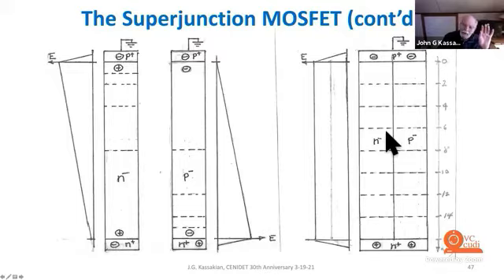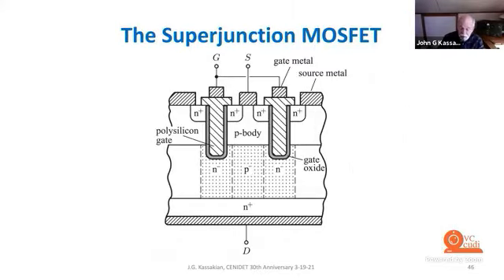And it actually gets a little better than that, because I can also increase the doping concentration in these columns if they're narrow enough and still maintain the continuous equipotential across this boundary. And so not only can I support a greater voltage here, but I also have reduced the resistivity of this region when it's conducting. So that's the basis of the superjunction MOSFET, which has, to a large extent, displaced the conventional MOSFET.